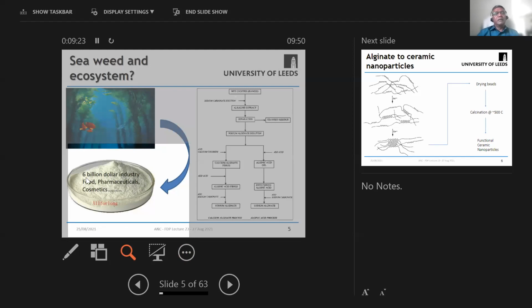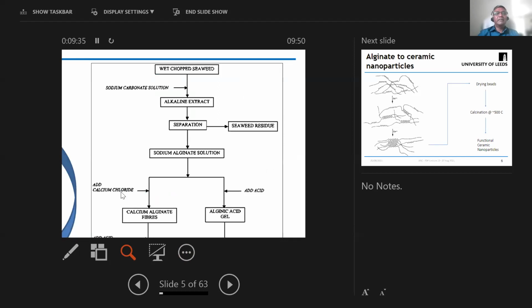Okay. So what is done is the seaweeds are chopped initially or shredded, and sodium carbonate solution is added. This is a well-known process, so I won't go into details about how it happens, but I'll just go through the steps that are followed for everybody's information. The seaweeds are chopped and treated with sodium carbonate solution to extract the alginate from the chopped seaweed, because sodium forms a compound with alginate or alginic acid present in the chopped seaweed. It is separated from the residue. The residue is the seaweed residue, which is discarded. And the sodium alginate solution that is produced as a result of sodium carbonate treatment is then further purified.